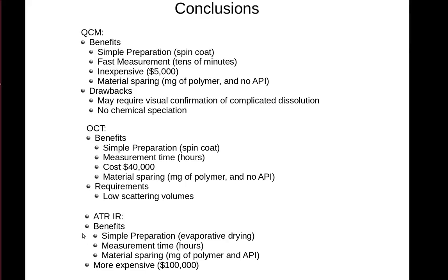And finally, if we want to try to understand the multiple components dissolving, we can use some spectroscopic techniques, this attenuated total reflectance. Again, the sample preparation is quite easy due to the geometry of the setup. We can't spin coat, but we can use evaporative drying. The measurement time is a bit longer again because the film thickness is a bit bigger, but it is overall material sparing compared to a traditional dissolution measurement, and the instrument is a bit more expensive.